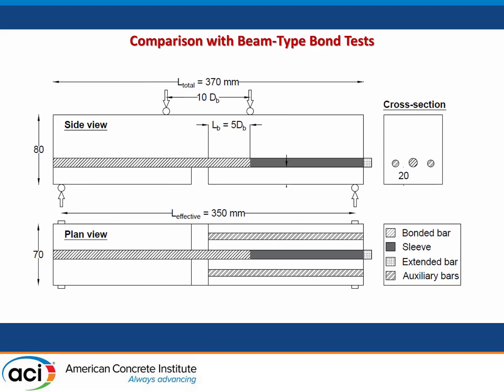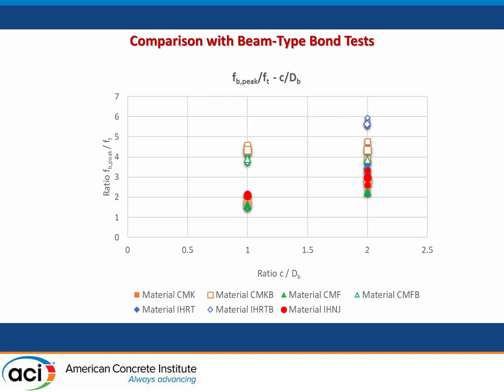At the same time, we did a comparison study where exactly the same materials, the same kind of bar, and the same casting were used in beam bond tests, where again the development length would only be five times the bar diameter, adjacent to a notch. The notch was in the constant moment region, controlling the magnitude of the force that we would be inputting in the bar. And what we saw in summary are the following results.